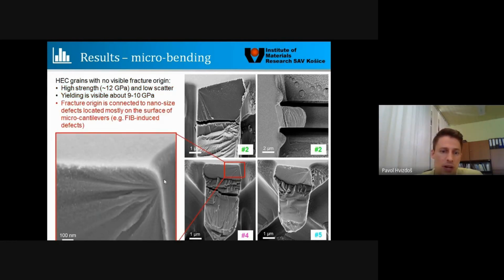The fracture origin turned out to be connected to some defects on the side, most probably FIB-induced defects. Because the stresses are the highest at the fixing, and because the defects are on the side, they usually started some crack initiation and fracture, and this caused this kind of Hackle regions in all cases that we observed.